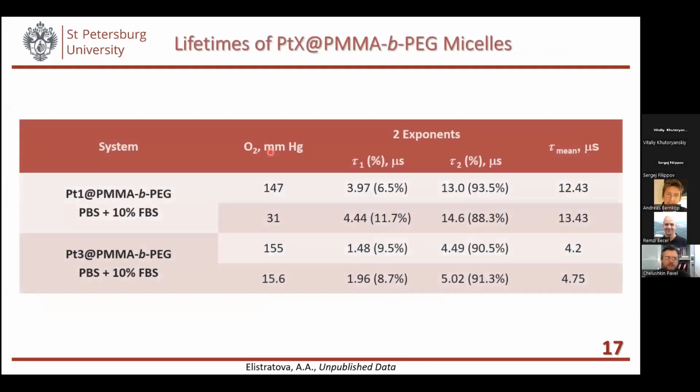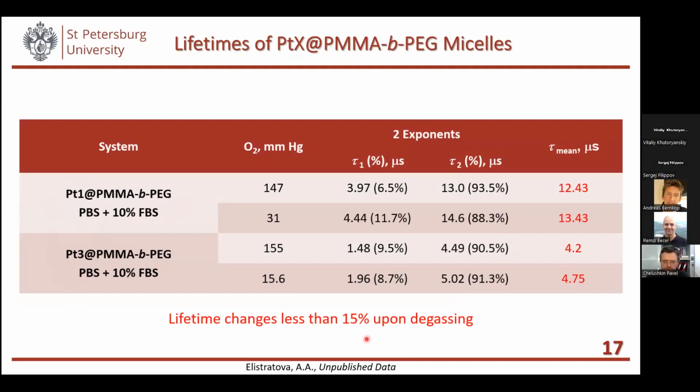Unfortunately, the micelles bearing platinum complexes didn't work because they were actually weakly sensitive to oxygen. In this case, we see only 15% change of lifetime upon degassing, and I think it's not high enough for further development of the systems.